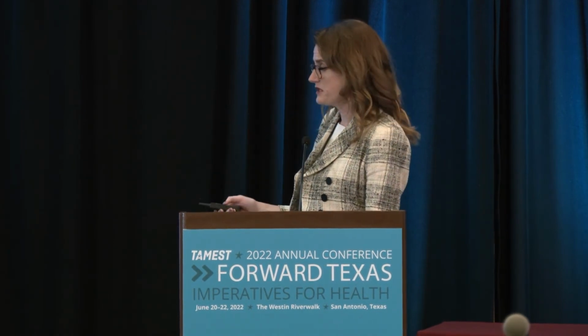We're getting a capacity around 30 milliamp hours per gram. For an organic battery, it's okay for a full cell battery. Compared to a lithium-ion battery, it's only a fifth of the capacity of a lithium-ion battery. So you can see there's immense research opportunity to improve our performance.